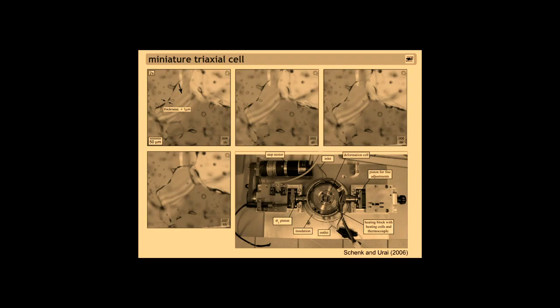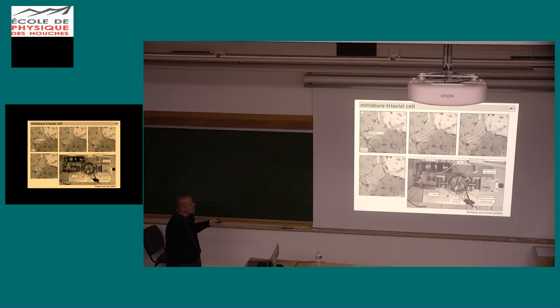So this grain boundary fluid film was of course elusive for a long time because it's not so easy to see 40 nanometer thick fluid films. We studied it using magnesium chloride salts in a miniature triaxial cell where we could actually watch these grain boundaries. Here this is a grain boundary, and you can see these fluid inclusions which are connected to the grain boundary that is migrating. Here the grain boundary changes. There's another one. There is another one here.